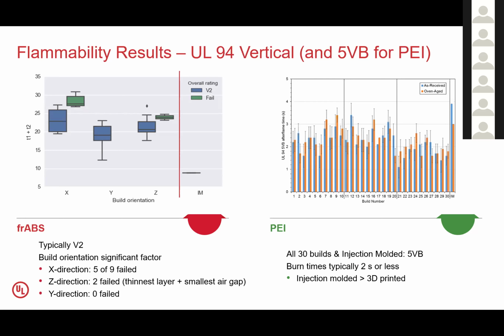When we did 3D print that filament, the ABS filament, we saw a wide variety of performance. Many of our 3D printed specimens out of our 30 different variations did achieve a V2 rating, but we also had a number of them that did not pass the vertical flame test. So that's a problem where that material, it's the same material, it was just printed differently, may pass, might not pass. And we found that build orientation was the key factor for differentiating on performance, whether it's printed horizontally or if it's printed vertically in the vertical orientation.